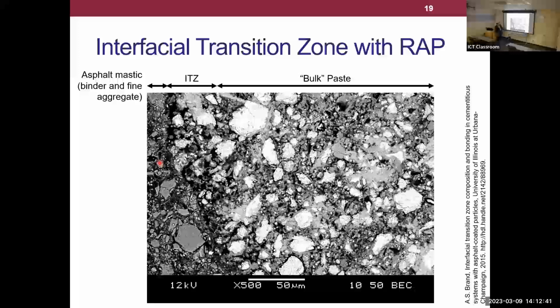Again, the grayscale is a little bit difficult to see here, but you can clearly see you have this zone that is definitely more porous, right near that RAP particle surface relative to what would be the bulk. You can definitely see a lot more porosity here.